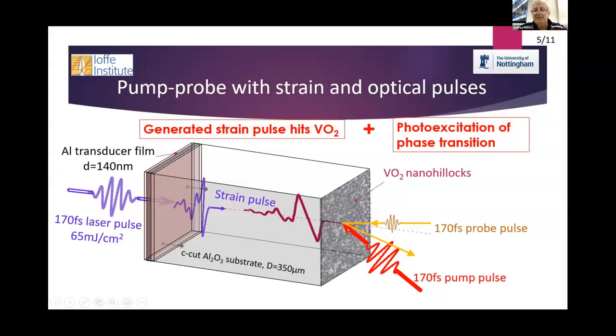Which demonstrates the pulse excitation, pump excitation of the phase transition, and we may control the amount of material which possessed the phase transition by measuring the reflectivity of this probe pulse, and then I shall show the examples how it works.